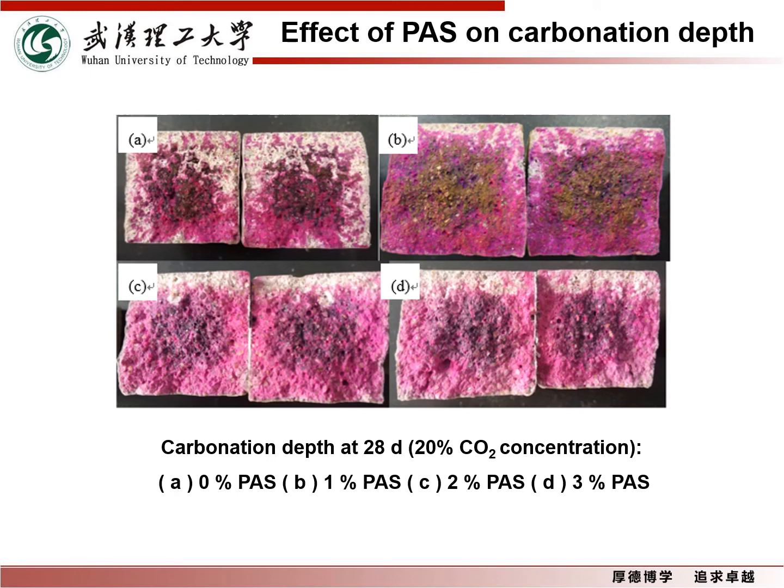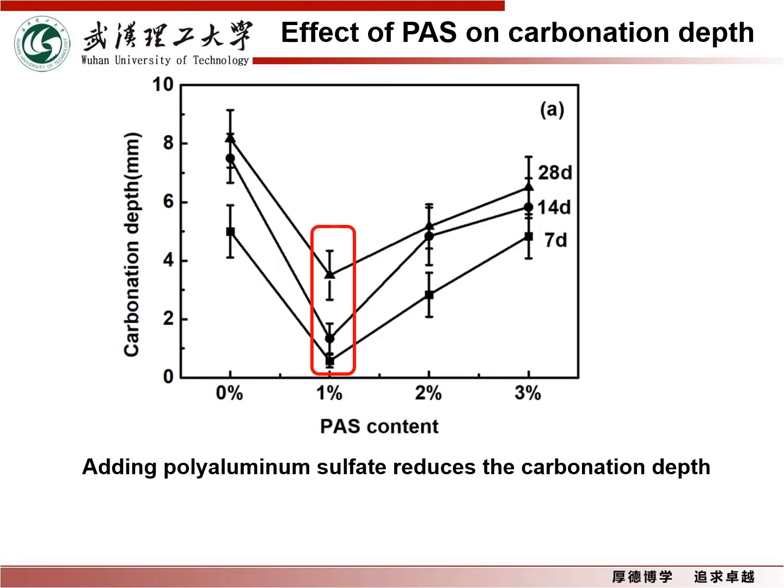This is the image of the carbonation depth test after carbonation for 28 days. This figure shows the effect of PAS on the carbonation depth of the paste after carbonation for 7, 14, and 28 days. Adding polyaluminum sulfate reduces the carbonation depth of the pastes.